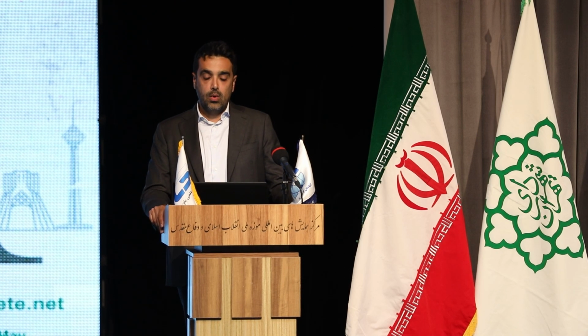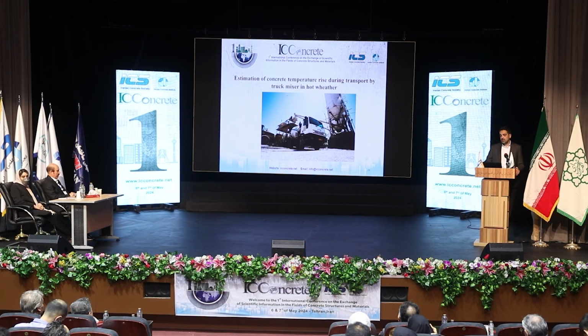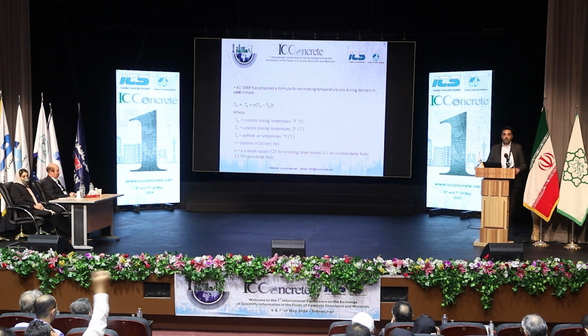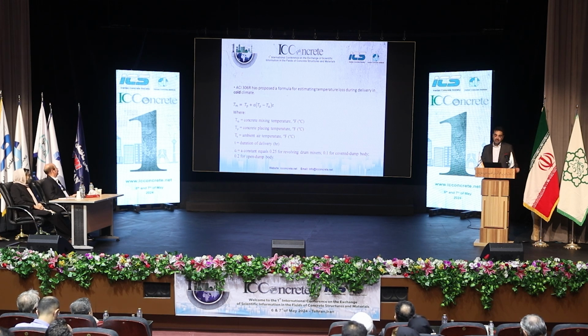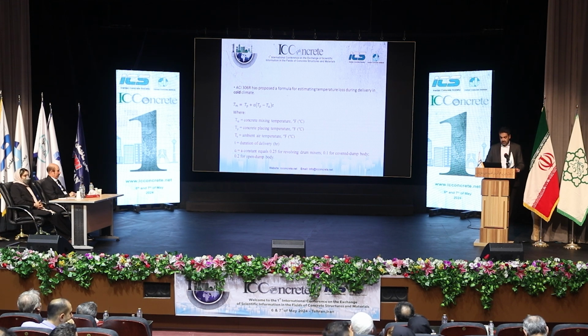In other work, we estimated the concrete temperature rise during transport by truck mixer in hot weather. There is a formula presented in the ACI 306 report for estimating the temperature of concrete at job site when we are subjected to cold weather. In our work, we made a formula for predicting the concrete temperature in hot weather situation during the delivery of concrete.